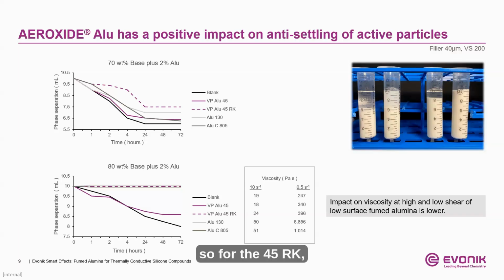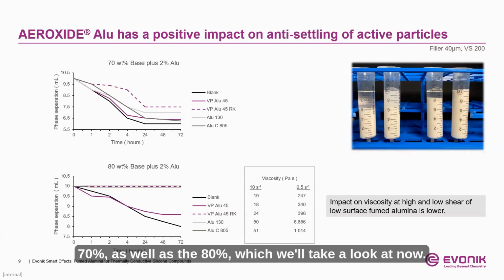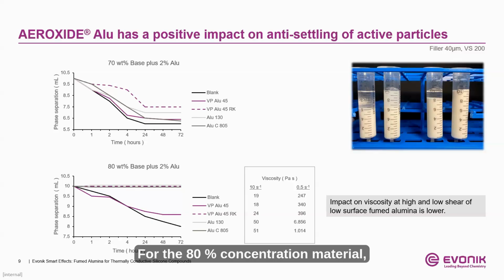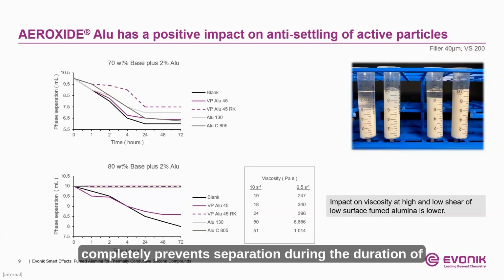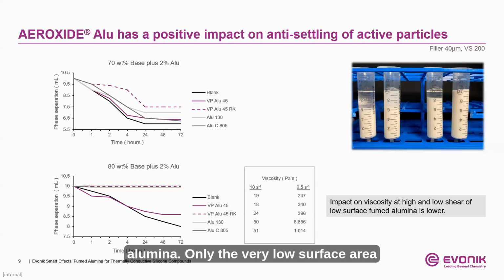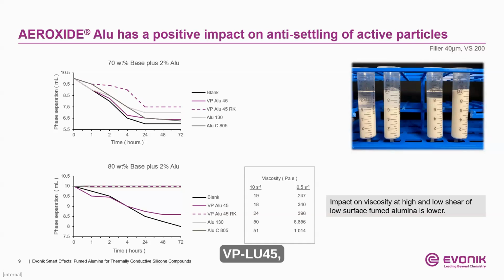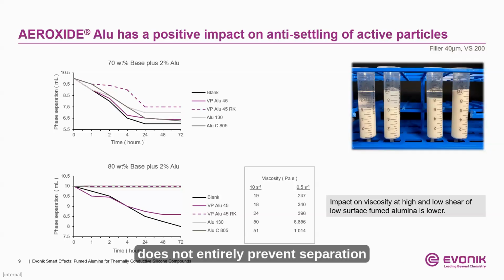And we see that, yes, for the 45 RK, we do get greater benefits at the 70% as well as the 80%, which we'll take a look at now. For the 80% concentration material, we see a much different situation, with some samples exhibiting no degree of phase separation over a 72-hour period. Again, the hydrophobic VP Alu-45 RK, along with several higher surface area options in this instance, completely prevents separation during the duration of the test at the 80% concentration of spherical alumina. Only the very low surface area VP Alu-45, which is again hydrophilically treated, does not entirely prevent separation here.